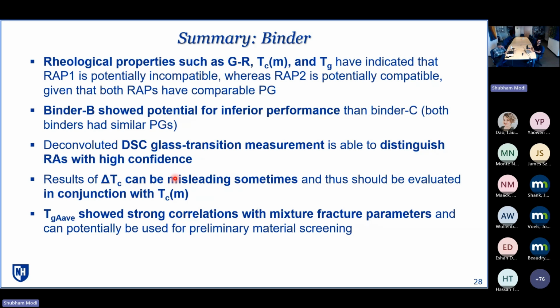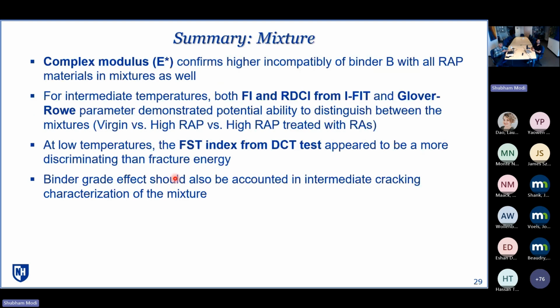And the TG parameter, as it has shown good correlation with mixture fracture parameters, can potentially be used for preliminary material screening. On the mixture side, the complex modulus test confirms the findings from the binder testing, and it differentiates between the binder sources. For intermediate temperatures, FI and RDCI from the IFIT test, and the Glover-Rowe parameter demonstrated high potential ability to distinguish between these mixtures. For low temperatures, FST appeared to be more discriminating than the fracture energy by itself, and binder grade effect should be accounted for in the intermediate temperature characterization.